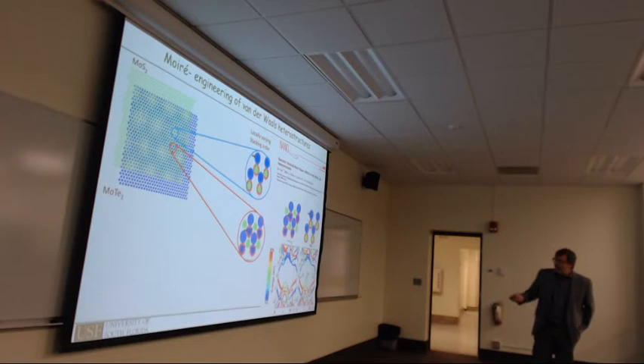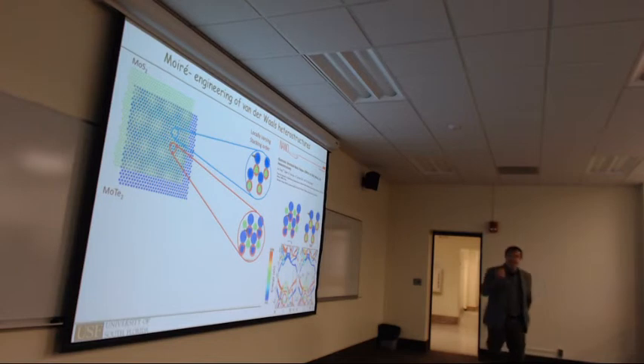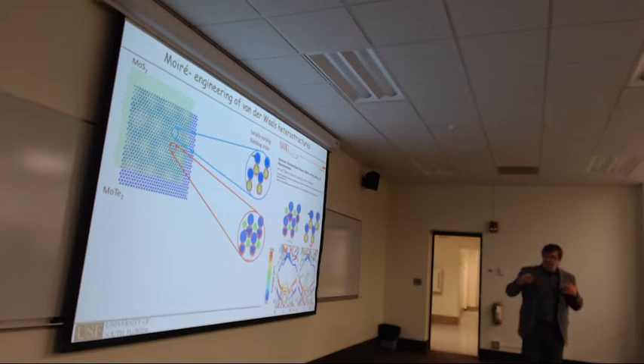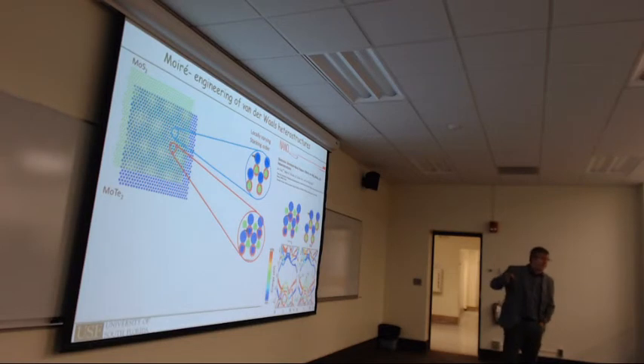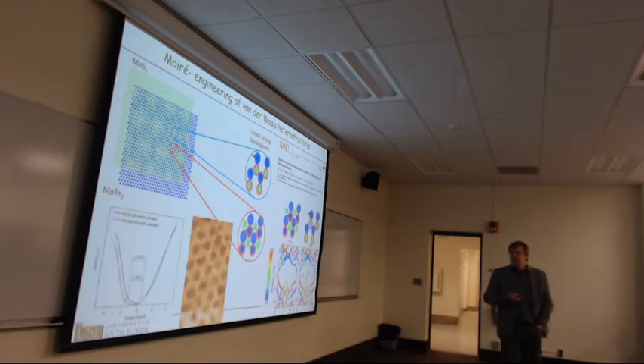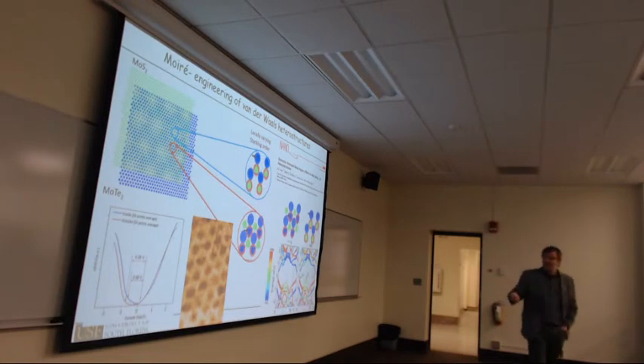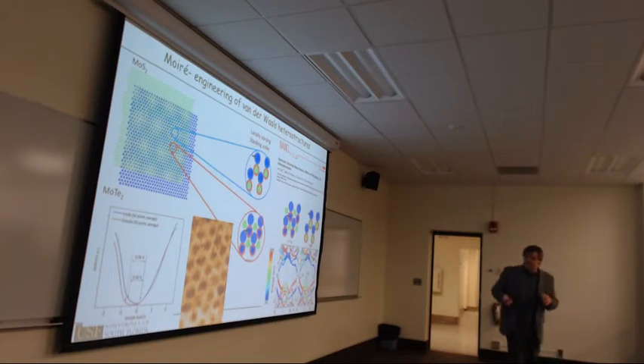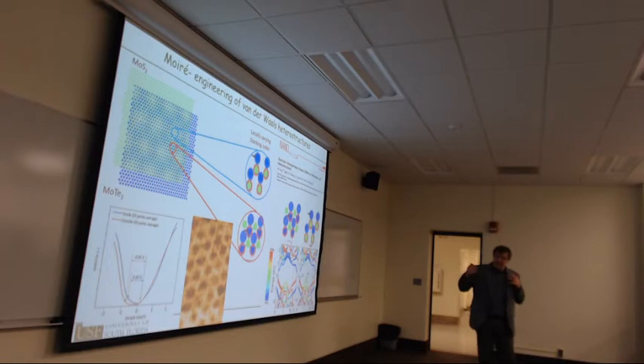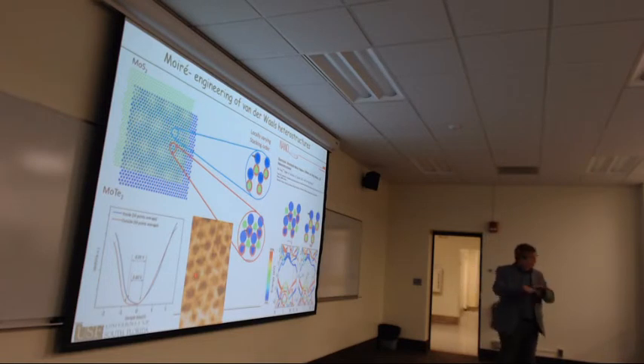So now what you have then, if this calculation is correct, is a variation of the electronic structure on this nanometer scale, as these are just a few nanometers apart, and you get a very modified electronic structure, or if you want localized kind of quantum dot structures in just the moire structure, or if you put two semiconductors on top of each other. We can do that here, molybdenum telluride on molybdenum disulfide, and do STM, and you really see this strong modulation if you set your bias voltage correctly, which suggests more than just a topographic variation.